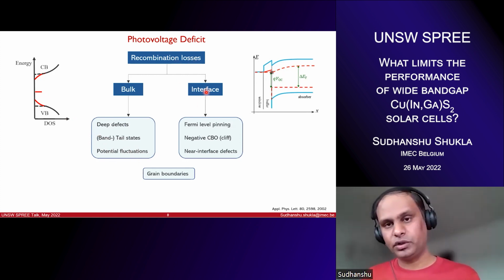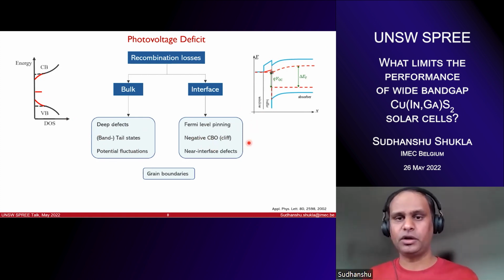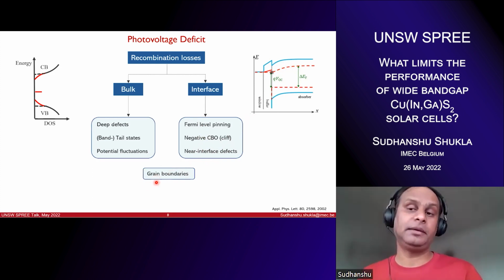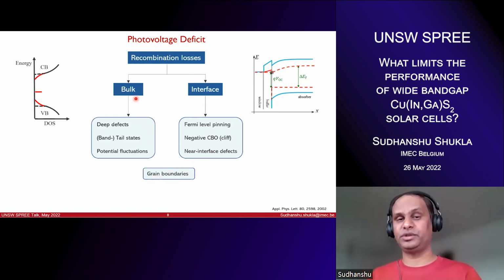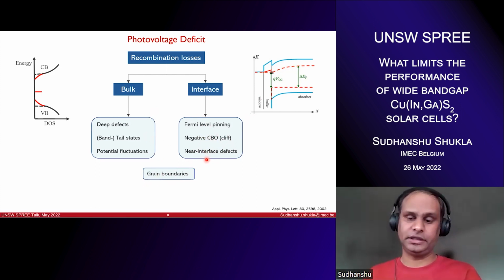And then you can also have recombination at the interface, which could be related to improper band alignment, the cliff type, we call it, negative conduction band offsets. We can have Fermi level pinning. So you have so many surface defect states that your Fermi level is actually pinned, and then your VOC is limited by that. You can also have something very notorious called near interface defects, which is neither explained by Fermi level pinning or conduction band offsets. This is quite tricky to deal with. And another recombination that can happen is at the grain boundaries, which I'm not even putting in the bulk or interface. I think they lie somewhere in between. So they are both interface and bulk.